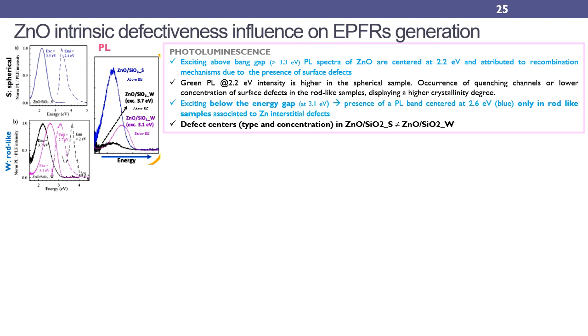The choice of the synthesis and growth parameters influences the morphology and the structure of the zinc oxide nanoparticles attached on the silica supports, and thus the intrinsic defectiveness of the samples. Photoluminescence and photoluminescence excitation measurements reveal that zinc oxide grown on spherical support can be excited with energy above the band gap, giving rise to a green luminescence at 2.2 electron volt. The origin of this band is under debate, but it may be due to surface defects.